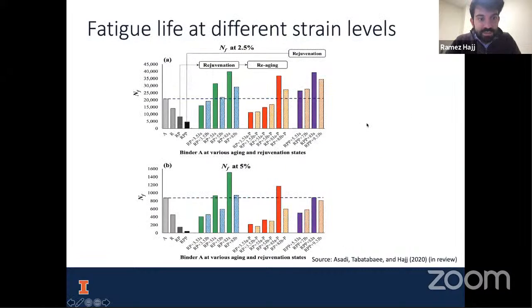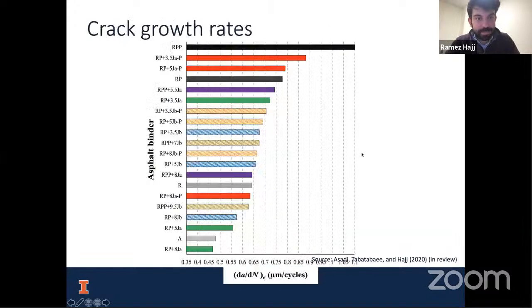We looked at fatigue life too. For example, same phenomenon here. As we rejuvenate, we see better than the original fatigue life. So even in the unaged original binder, we are actually able to restore better properties with rejuvenation. And this is at a lower level of strain, and this is at a higher level of strain.